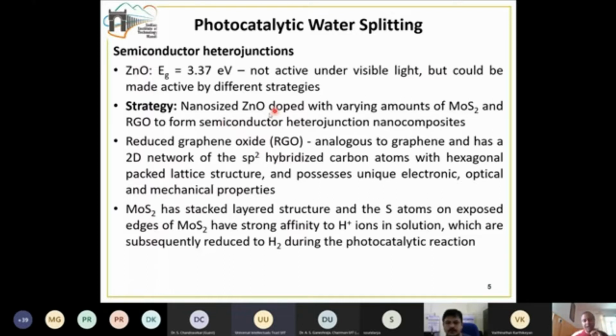Now, why do we need RGO and why do we need MoS2? RGO stands for reduced graphene oxide. This is very much analogous to graphene, because graphene is a single layer and is quite expensive, and the process to obtain it is also not so easy. So reduced graphene oxide is kind of a poor man's graphene, which can be easily prepared in the laboratory using the Hummers method, followed by subsequent reduction strategies. So it is analogous to graphene. It also has sp2 hybridized carbon atoms, it is a very good electron conductor, and it also possesses very good electronic, optical, and mechanical properties.